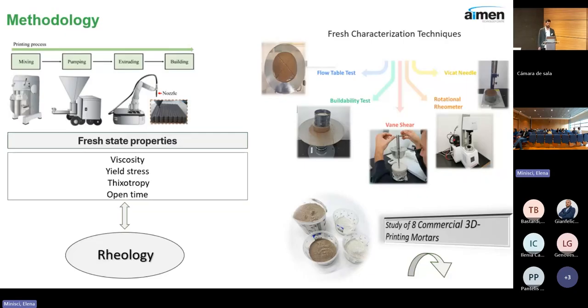So we started this line two or three years ago, more or less. We didn't know exactly how to optimize these materials. We knew at that time that rheology was crucial because the 3D printing process can be broken down into pumping, extruding, and building, and all of these phases are governed by rheology. So at that time, we decided to study 8 commercial 3D printing mortars, Portland-based, in order to obtain printability criteria that we will use as guidelines to develop our low-carbon cements.